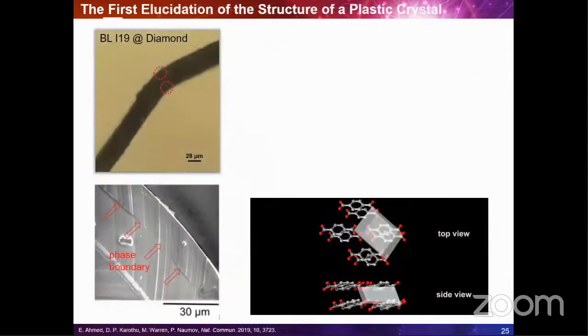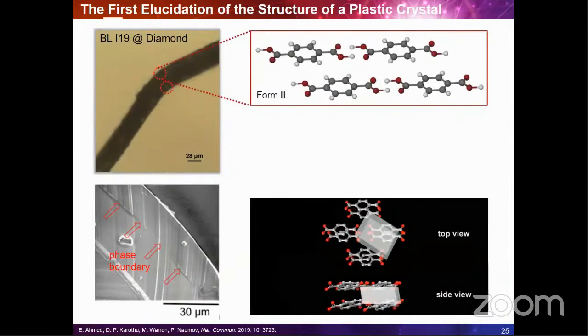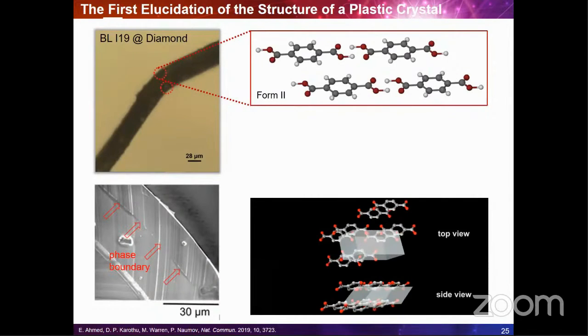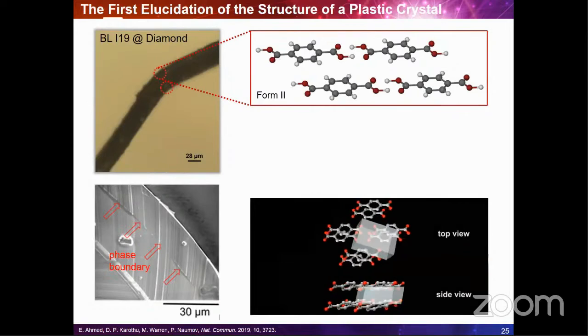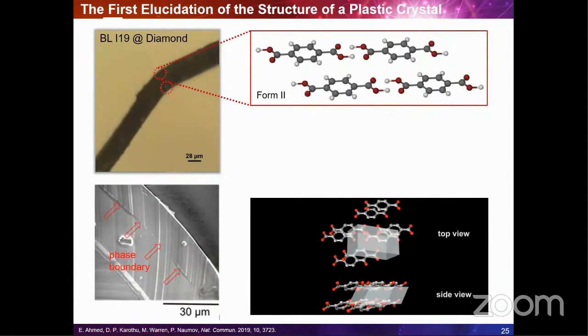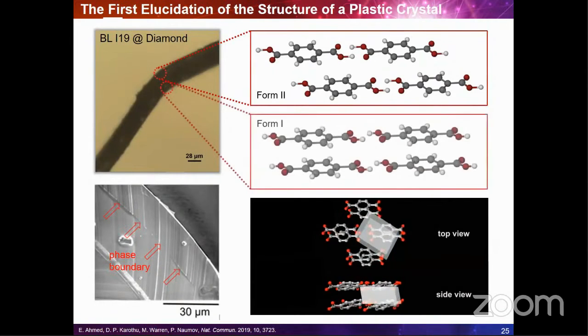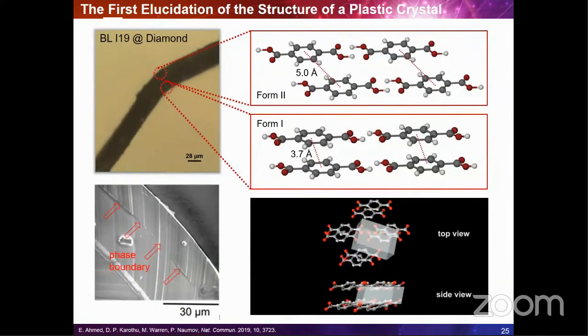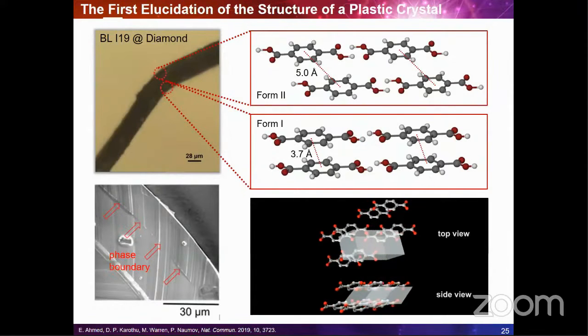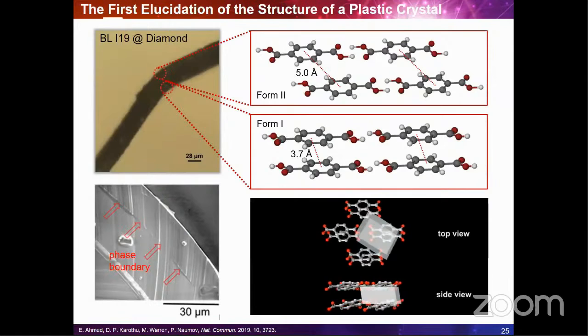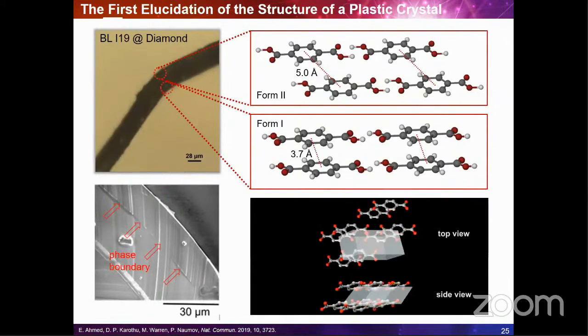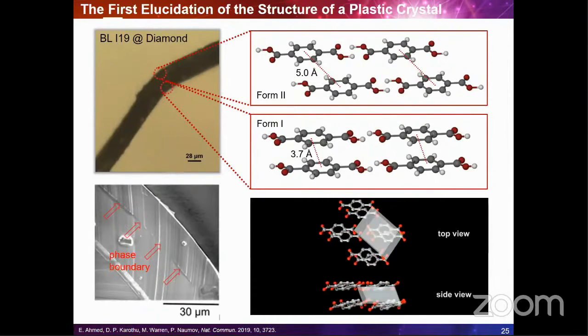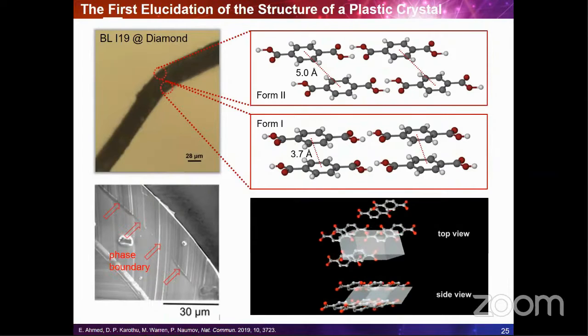In fact, we were so interested to see what is happening that we used a microfocus X-ray to study these crystals. So the bent crystal of the form 2 terephthalic acid was analyzed by using microfocus XRD using synchrotron radiation, and refinement of the crystal structure at the 2 points of the crystal, so outer and inner point, confirmed that the two phases coexist in the bent crystal, and their structures are identical to those of the pure phases. So this result presents evidence that the inner part of the crystal has undergone phase transition during bending as a result of application of local pressure, and that the two phases of the crystal coexist in the bent crystal. We think that similar memory and restorative effects are more common of other molecular crystals having metastable polymorphs, and of course it would be nice if they are investigated further.